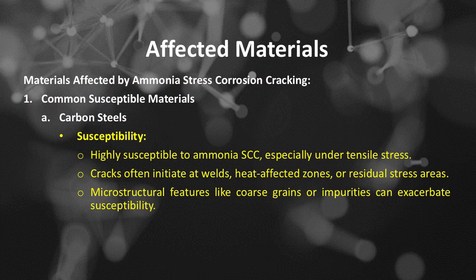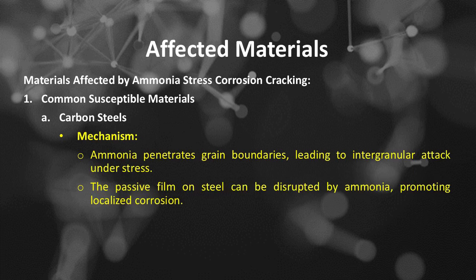Carbon steel's susceptibility: highly susceptible to ammonia SCC, especially under tensile stress. Cracks often initiate at welds, heat-affected zones, or residual stress areas. Microstructural features like coarse grains or impurities can exacerbate susceptibility. Carbon steel's damage mechanisms include: ammonia penetrates grain boundaries, leading to intergranular attack under stress. The passive film on steel can be disrupted by ammonia, promoting localized corrosion.